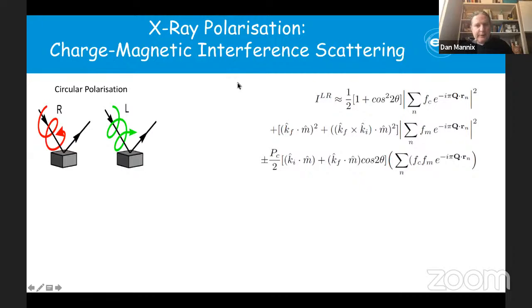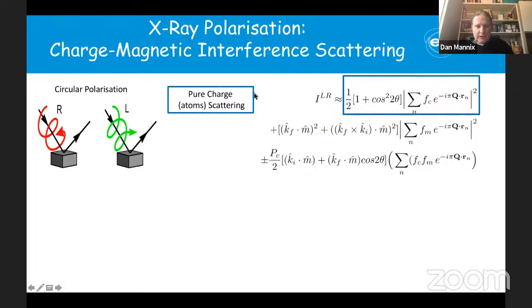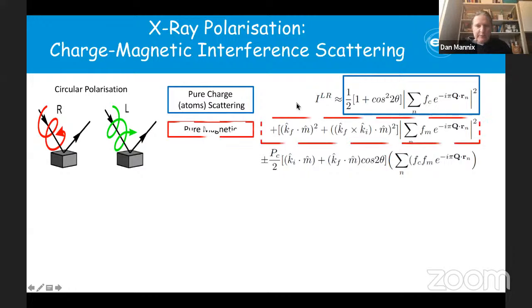What are the intensities that we would expect for circular polarized light? It basically breaks down into three terms. The first term here is this charge scattering term. This is the atomic scattering, and it's simply related to the FC term, the number of electrons that I showed before. There's also a polarization prefactor. The second term is pure magnetic scattering, and that is related to the strength of this FM term, or it's usually dominated at an absorption edge by this resonant scattering response, those peaks that I showed in the previous slide. There's also a prefactor term, which is dependent on the magnetization direction, the moment direction, and ki and kf are simply the incident and scattered wave vectors.